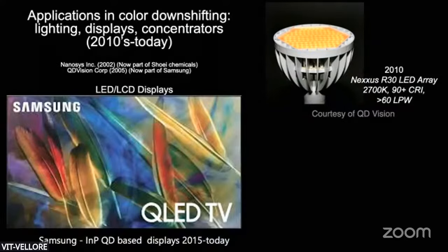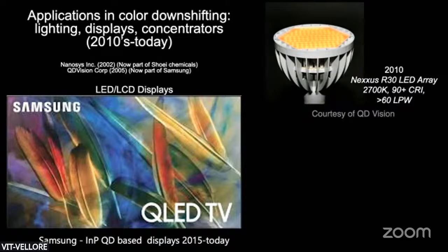Samsung went ahead and invented indium phosphide quantum dots, how to do that chemistry without cadmium, and figured out how to do the scale up, how to go from pieces made by hand essentially to scaling up into these huge 500 and eventually 3,000 liter containers to do the same chemistry. That was really hard. It was very expensive, hard and expensive, but they did it. And they bought QD Vision.